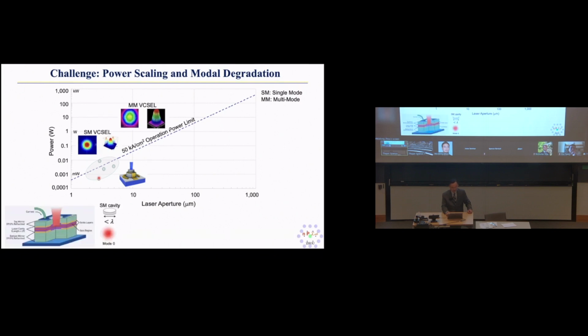And intrinsically, if you look at the VCSEL here, here's the cross-section of the VCSEL structure, DBR top and bottom, and that's the emission aperture here. When the aperture is very small, less than the lambda, the wavelength of the material, you get a nice single mode operation. However, when you get a very large aperture, you get multi-modes. That's where the issue intrinsically limits the power scaling while maintaining single mode operation. So the question is, can you get high power single mode lasers, right?